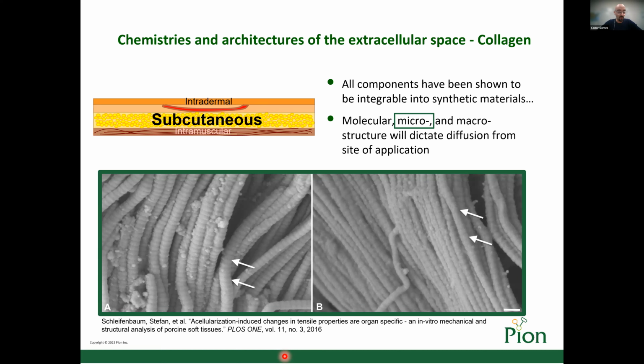a primary component of that is going to be the available void space in these materials. And this type of D-banding in this microstructure is actually going to come into play, because whether your injection is going through each of those D-bands or it's interacting directly on a collagen fiber is going to have a role in the response you see in the clinical release.